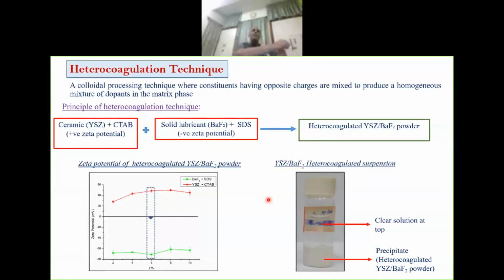An example of a process, we call it heterocoagulation. We take yttria stabilized zirconia hard coating. Onto that, we wish to put in barium fluoride, a high temperature solid lubricant. If you try to mix them, they tend to segregate. What will you do? You bring in another chemical here. It's called CTAB, a surfactant. They're available in detergents. And you bring in here SDS, another surfactant.